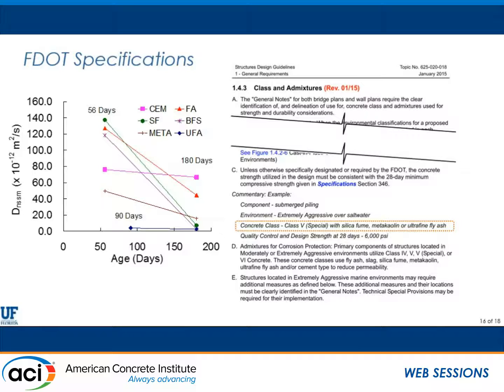One thing I didn't mention is that they require a curing regimen in the yard. The contractor is required to leave the piles in the forms and cover them with burlap and wet cure them for 3 days, if you can believe that. So, a good curing process with that.